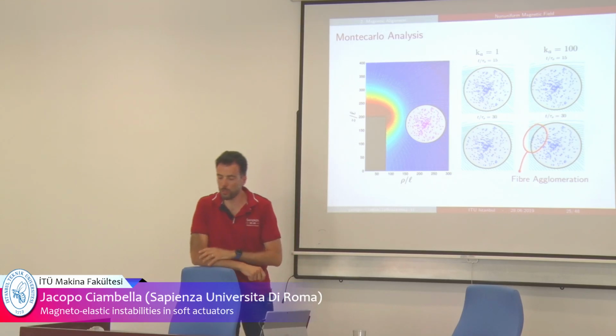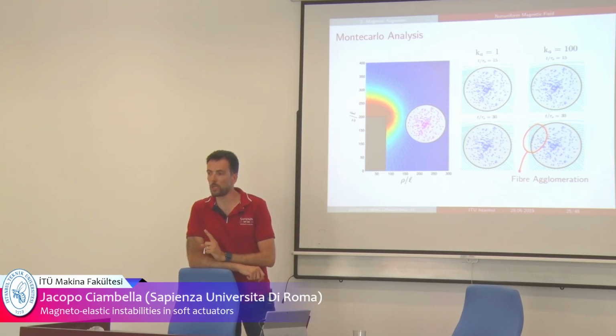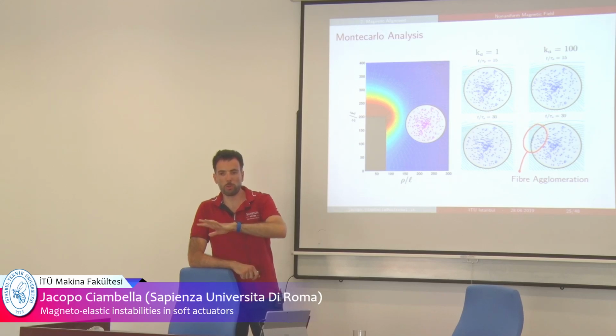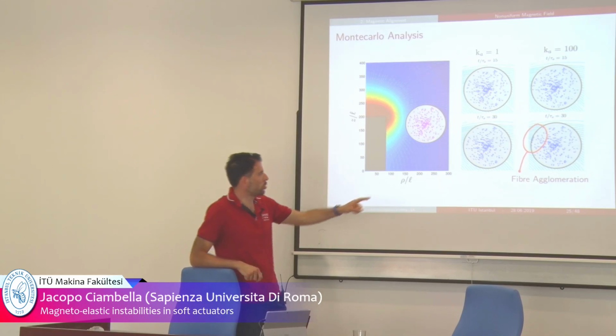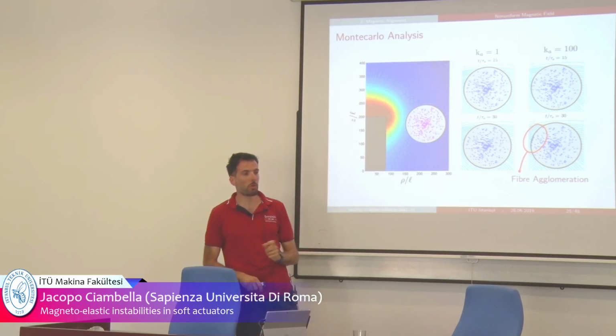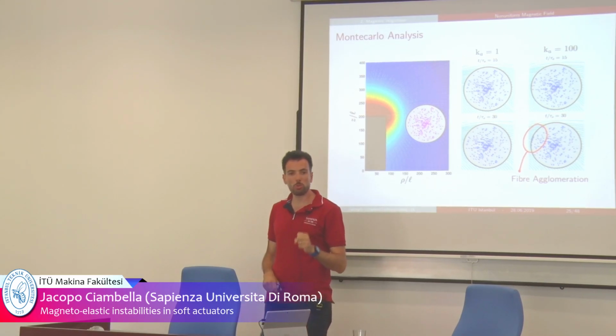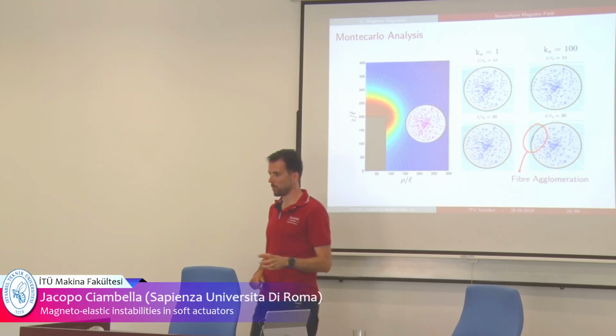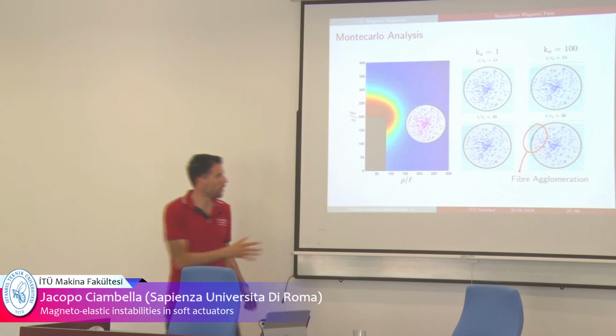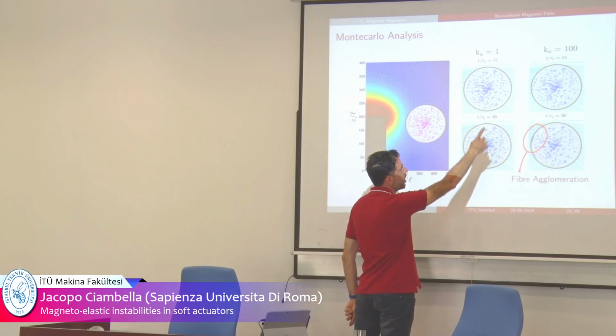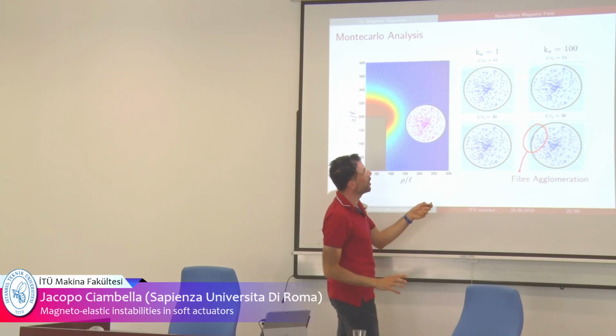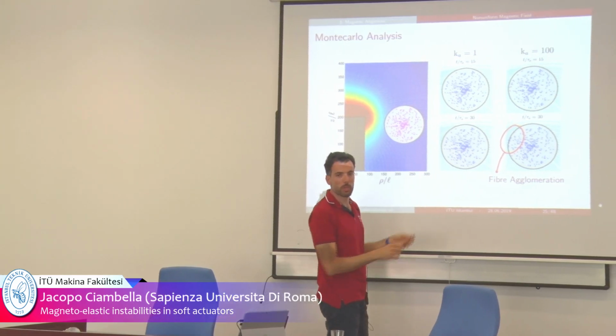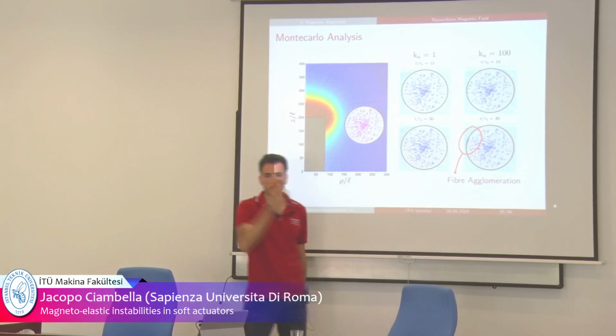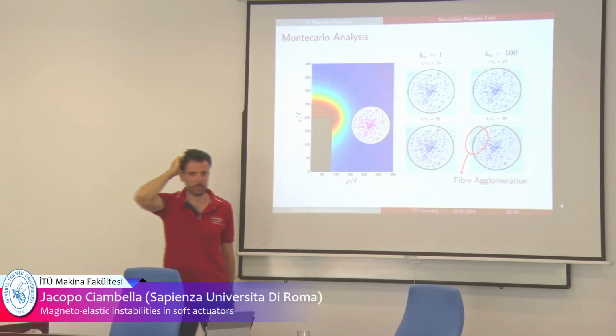Why this simulation? Maybe I wasn't very clear before. What we wanted to study was to find an optimal configuration which allows you to have particles rotating within your specimen according to the field lines, but with a very low translational velocity, because you don't want particle agglomeration. Ideally, you only want the particle to bend with the field lines, but no agglomeration. For instance, Ka equal to 1 is okay. With Ka equal to 100, you start seeing particle agglomeration. And this would be detrimental for your specimen, because the mechanical properties close to the border will be very bad.